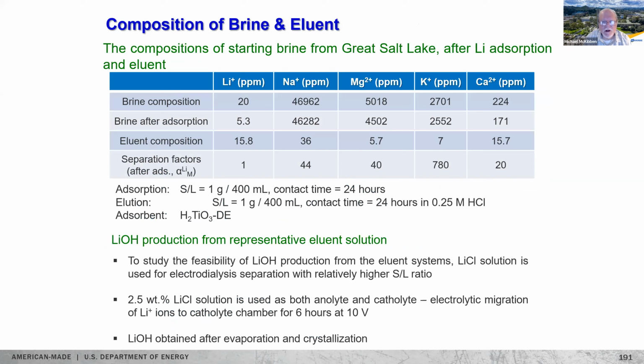So here are some results of our adsorption-desorption experiments on the Great Salt Lake brines. These are at room temperature, showing the brine composition before adsorption, brine composition after adsorption, and the eluent composition. Note the separation factors or alphas showing how selective the adsorbent is for lithium versus competing mono and divalent cations. Solid to liquid ratios for the experiments were 1 gram adsorbent per 200 to 400 milliliters of brine with 24-hour contact times at room temperature.